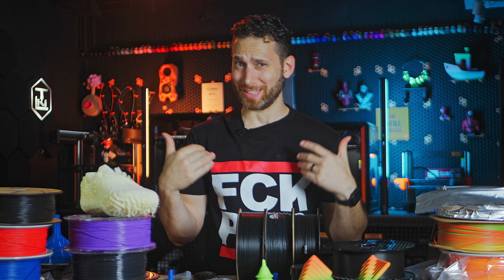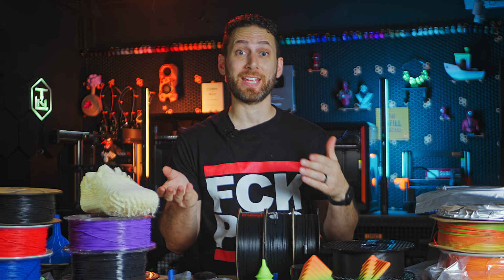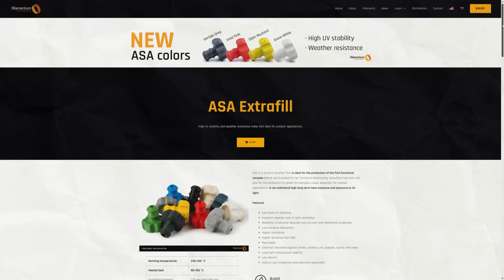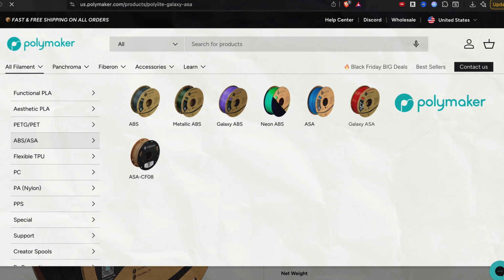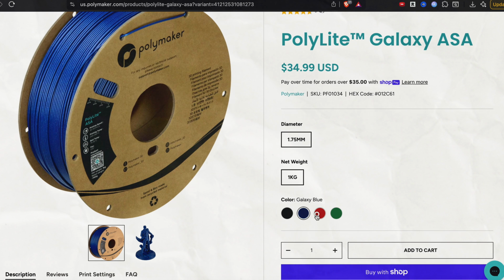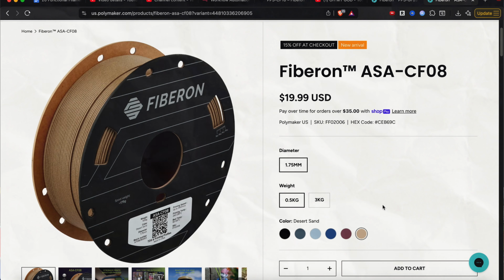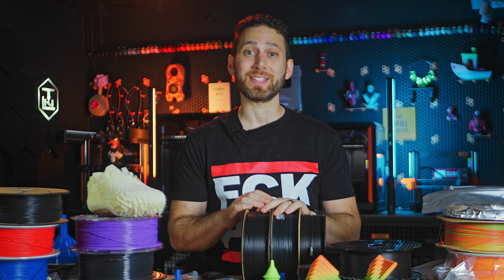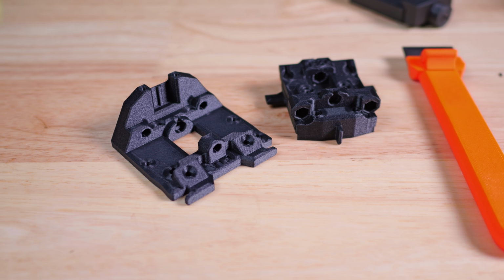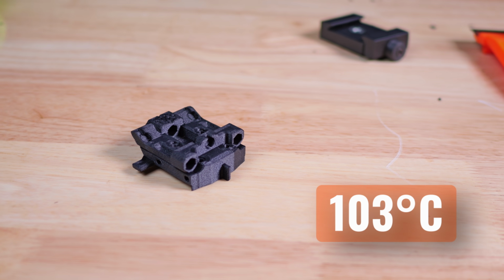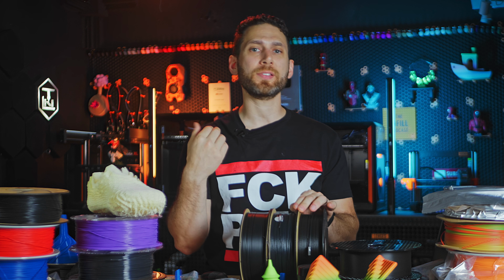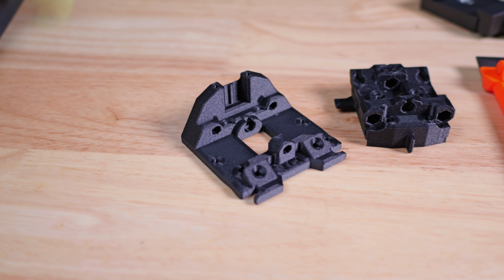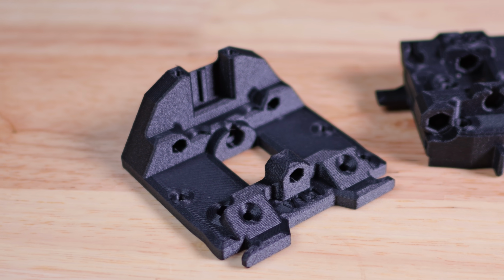Up next, I feel like I should just briefly mention ASA-CF. When I was a lass, most brands didn't even offer a wide variety of ASA colors, but now we're seeing a lot of major brands like Filamentum and channel sponsor Polymaker come out not just with plenty of colors of ASA, but even colored ASA-CF. Now, as with all the carbon composite filaments, the addition of carbon fiber is going to give you a nicer surface finish, as well as increased heat resistance, in this case up to 103 degrees C, as well as more rigidity and better dimensional stability. It really works great in any situation where you'd normally use ABS, like these Voron parts that I printed. But just be careful not to place PCBs against them, because carbon does conduct.